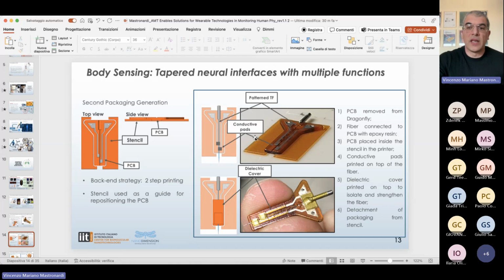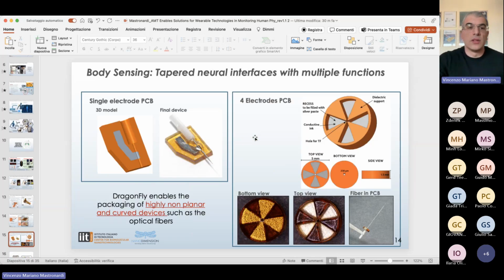A covering that is made of both dielectric ink and conductive ink. The dielectric ink acts as a protective coating on top of the fiber, and the conductive ink is printed directly at the same level as the pads located on the fiber. According to the number of electrodes made on the fibers, we can print different configurations of our PCB, from a single electrode up to 4 electrodes, engineering the layout and the final design of the PCB itself.